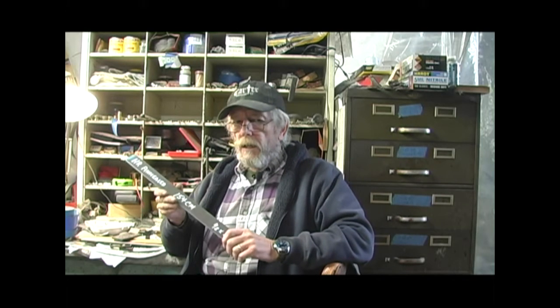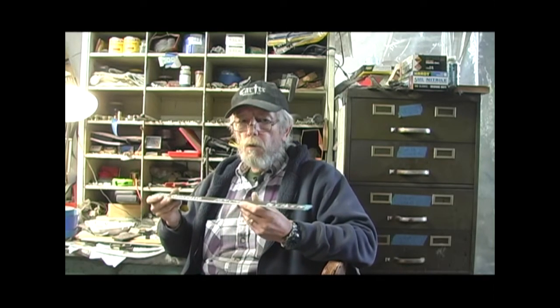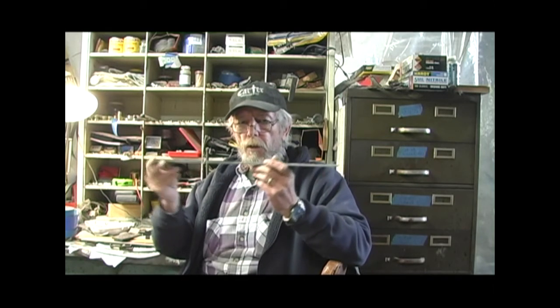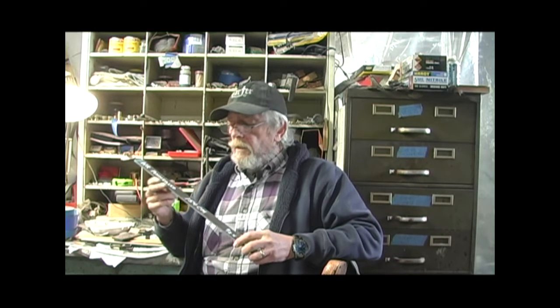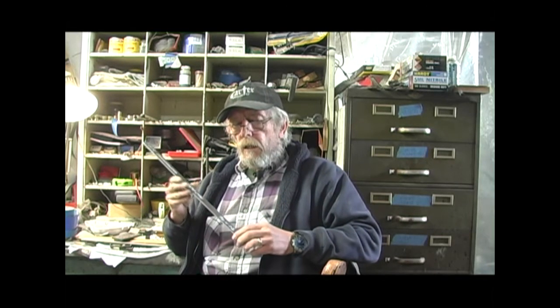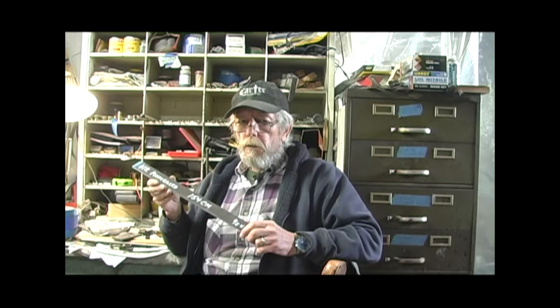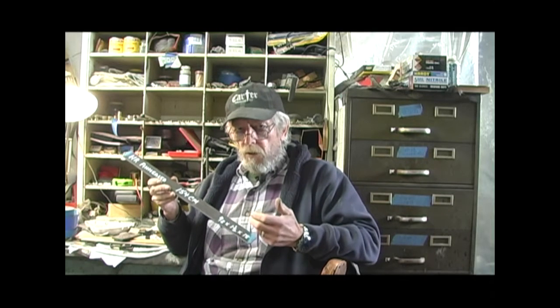Now the steel, when I buy it from the mills, I buy it in the annealed state. It's generally hot rolled through a series of rollers until it gets down to the thickness that they're producing at that time. And it's annealed where it's heated to a certain temperature and allowed to cool slowly. And in the annealed state, the steel is relatively soft. It's easier to work. You can grind it, you can drill it, and cut it fairly easily. After it's hardened, you can't drill it. It's as hard as your drill bit. So that's what the heat treatment does: it makes the steel hard and stabilizes it.